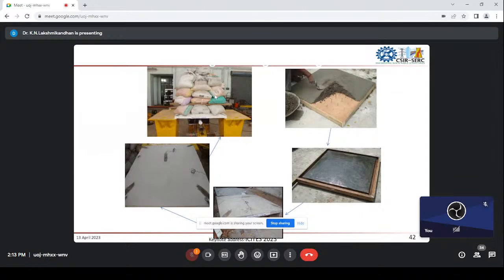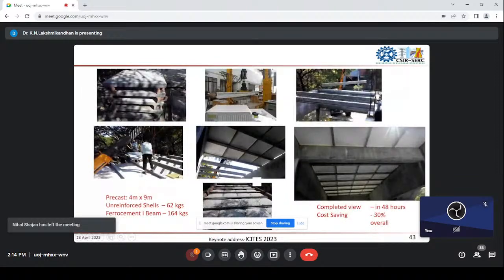That is the beauty of the system, and the thickness of the shell is 10 mm, and no reinforcement is provided in the shells. The shells you are seeing here are without any reinforcement. So this is a typical implementation. These are ferrocement I-beams we developed and tested, with very excellent ductility characteristics, and this is the implementation of the shell. In total we used 32 shells. 32 shells means 32 into 62 kgs. That's the whole weight of the roof for a span of 4 meters by 9 meters. So this is a typical view.